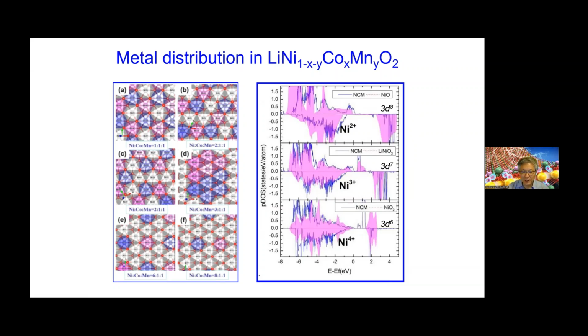So this is complex enough. How to handle it? If you have pure lithium cobalt oxide, all the atoms are cobalt, so that is pretty fixed. But if you have multiple elements, then you have to consider many possible configurations. Even more complex than that, transition metal atoms are known to have multiple oxidation states. The reason why we call this electrochemistry is that chemical properties are coupled to electronic state.